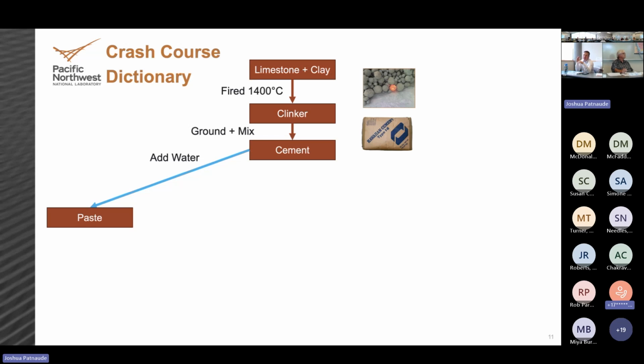So start with limestone and clay, heat it up, that produces clinker. Clinker is a reactive ingredient. That's the majority of the mixture in the bags of cement that you buy at Home Depot or from Lafarge or whatnot. So if we take that cement, that dry reagent, and just mix it with water, that gets us a paste. Once it hardens, you've produced a cement paste. If you take cement, water, and again add in sand to it, you get mortar.